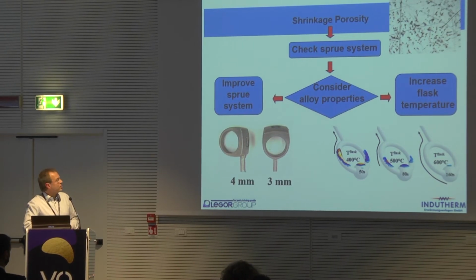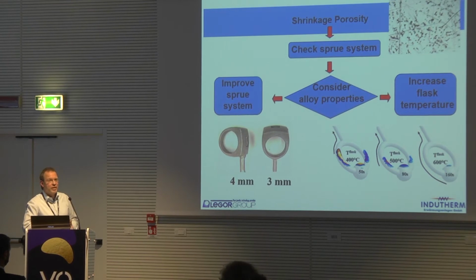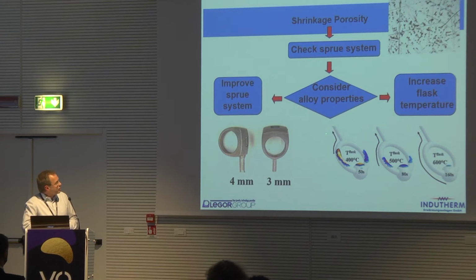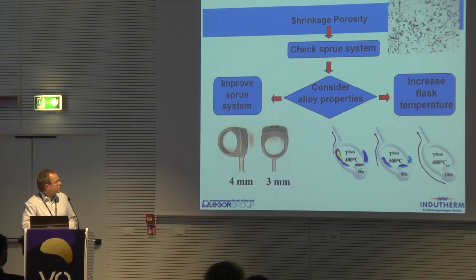Within the gold alloys, the higher melting ones, palladium white golds, are more susceptible to shrinkage porosity. And then the very high melting alloys, platinum or palladium based, are even more critical. So what can you do? First of all, the best option always is to improve the sprue system.